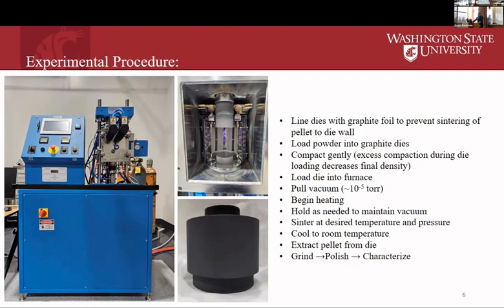You load your die and compact your powder gently initially. We found it was very important to compact the powder in a specific way, because compacting it too vigorously can lead to materials from the die becoming embedded in the powder, and thus in your final sample. Once you've loaded your die, you pull a vacuum and begin heating.